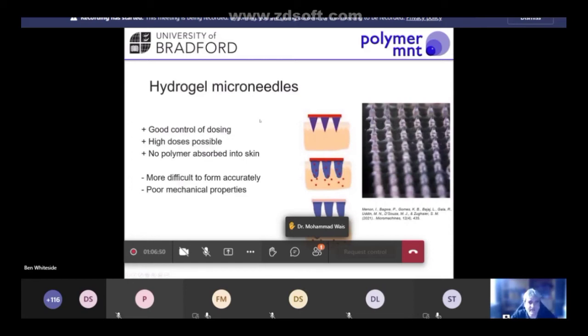And lastly, but not least, we have hydrogel microneedles. Hydrogel microneedles are very similar in some ways to the dissolvable microneedles, apart from the fact they don't dissolve. Basically a hydrogel microneedle consists of a hydrogel that contains your drug, your active pharmaceutical ingredient. And when that is placed into the skin, the hydrogel will absorb moisture, water, from the area, it will swell, and the swelling of that hydrogel dramatically improves the diffusion of materials through that hydrogel.